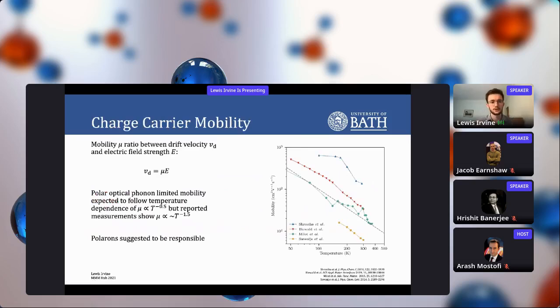Okay, so with that, we now want to start to calculate some charge carrying mobilities, because that's one of the observables that can get measured. We're going to define the mobility as the ratio between the drift velocity and the electric field strength. One of the curiosities in halide perovskites, especially with MAPI, is that you have a mobility that follows about T to the minus 1.5 across a range of different experimental techniques that give different orders of magnitude, but the same temperature dependence. Whereas if you just took standard textbook theory, you'd actually expect a T to the minus 0.5 temperature dependence, assuming Fröhlich scattering with polar optical phonons. And so polarons have been suggested to be able to explain this.